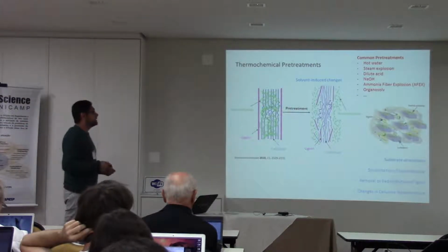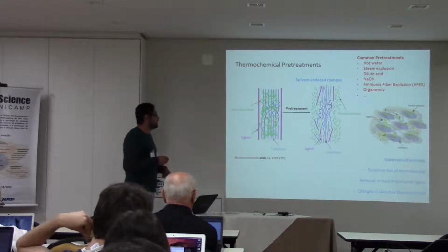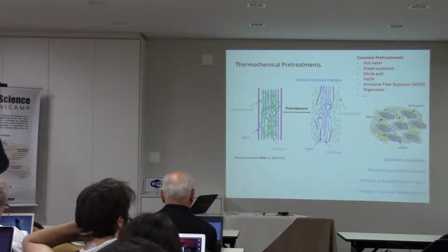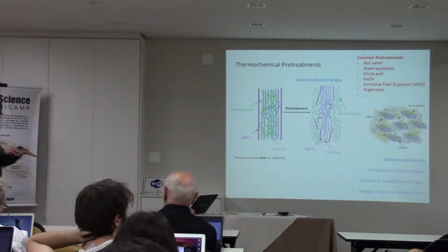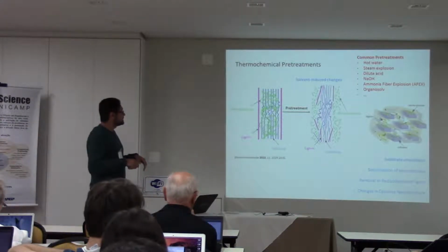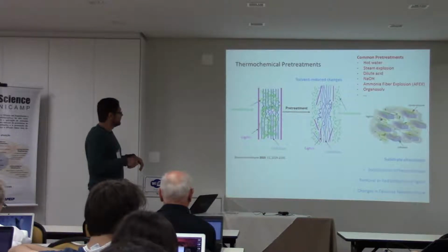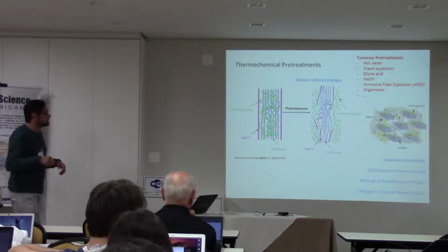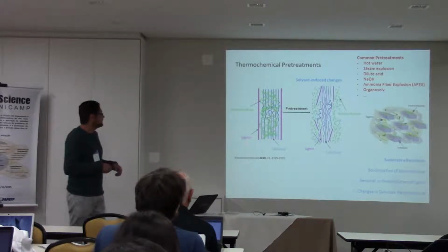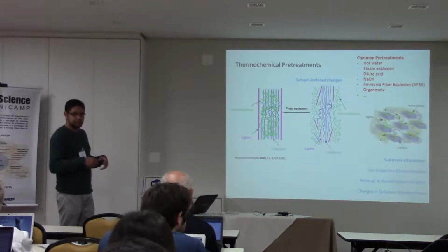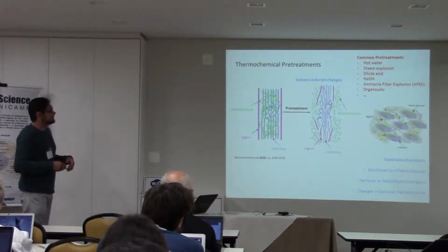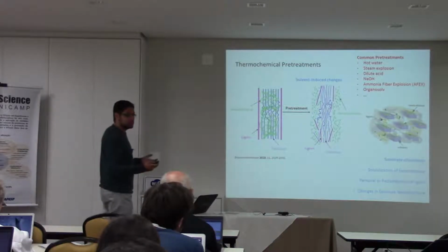One of the changes that happen when we submit the cell wall to pre-treatments is the solubilization of the hemicellulose, the carbohydrate that remains adsorbed on the cellulose. The polymer becomes lots of monomers and oligomers, right? And the lignin barrier is also removed or translocated to other parts of the cell wall, so that the cellulose becomes exposed to enzymatic attack.